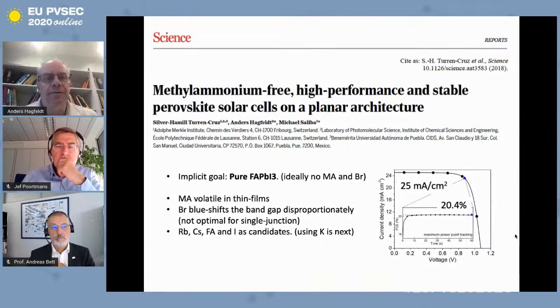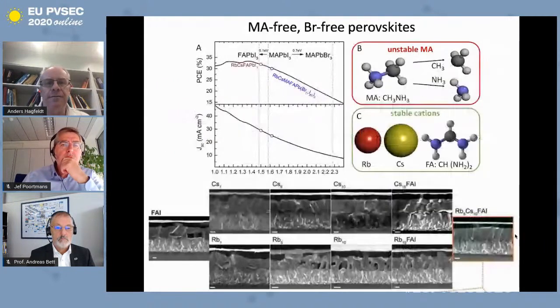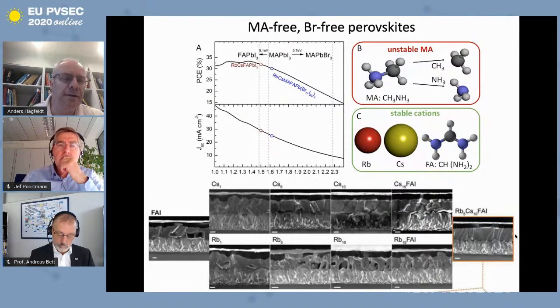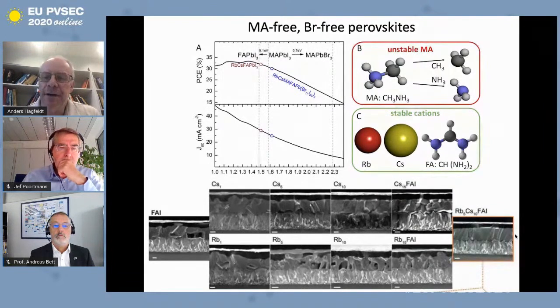And the important thing here is to say that the goal for us is really to go for pure FA, formamidinium lead I3. We want to avoid the methylammonium for stability reasons. It's a volatile cation. We want to avoid bromide because that increases the band gap. And here we found a recipe with our compositional engineering and reached efficiencies about 20%. And it really shows, if we look into the cross-section SEM pictures, where we from the left go from the formamidinium, where we have, as you can see, maybe voids and holes in the structure. Then we add 1, 5, 10, 15% cesium to the FA and get fairly good morphologies, monolithic grains, and so on.